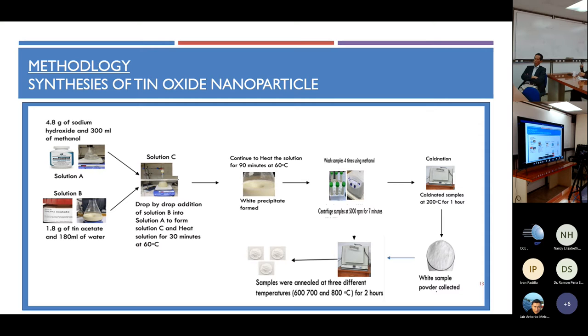I'm taking 4.8 grams of sodium hydroxide and mixing it with 300 ml of methanol to make solution A, and 1.8 grams of tin acetate mixed with 180 ml of water to make solution B. I put the tin acetate solution in a burette and add it drop by drop into the sodium hydroxide solution. In parallel, I'm heating the solution for 30 minutes at 60 degrees Celsius. After that, I continue heating for 90 minutes at the same 60 degrees Celsius. Then a white precipitate is formed.